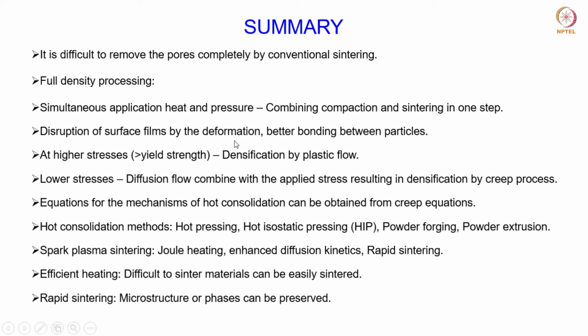So at higher stress levels, the densification can take place simply by plastic flow. As the yield strength of the material is exceeded, it will start to deform, and the densification can occur through plastic flow along the necks which develop between the particles. Okay. And at lower stresses, the diffusional flow will combine with the applied stress, resulting in densification by the creep process. Okay, and therefore the equations for the mechanism of this hot consolidation process can be obtained by suitably modifying these creep equations, taking into account the porosity which is present in the compact. So once we understood these mechanisms, we went ahead to talk about the different hot consolidation methods.